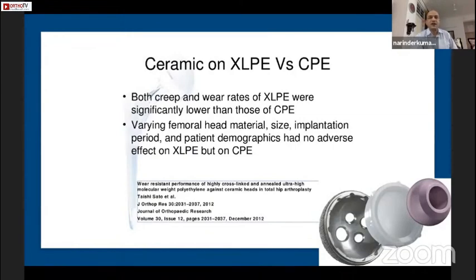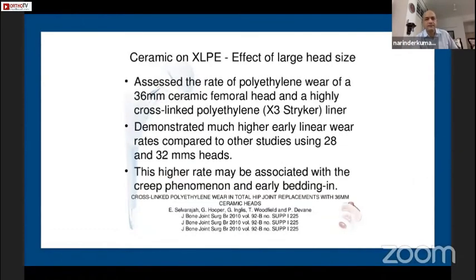Which brings us to the ceramic on cross-link poly or ceramic on conventional poly. Most of us are not using conventional poly anymore, because we know that with ceramic on cross-link poly, both the creep and wear rates are significantly better. And this is what most of the studies are also saying. But then the effect of large head size, because this is what most of us try to use.